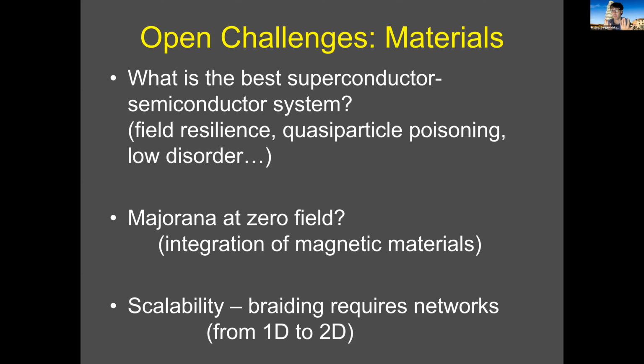It is an aluminum or a niobium superconductor. So maybe we need to create some kind of tunnel barrier between the superconductor and the semiconductor and control it, tune it, so that we decouple the semiconductor from the superconductor, and perhaps that would allow us to also reduce the number of subbands that we work with. Because from all these multiple quantum dots, our modeling shows that it's probably tens of subbands that we have under this superconductor. And that's just too much to clearly see Majorana.